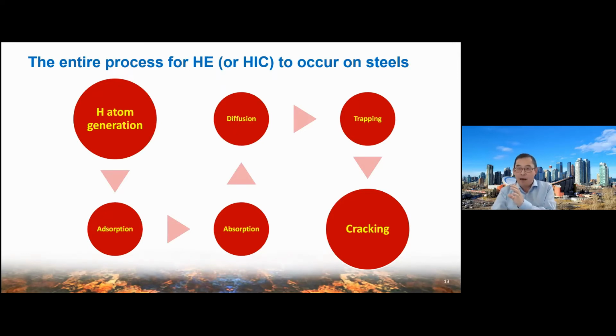All steels usually have typical metallurgical features and mechanical defects, so hydrogen can become trapped. That's step number 5, hydrogen trapping. When the stress, hydrogen and metal structure meet the condition, finally it can cause cracking. So you only have 6 steps at work to cause cracking of the steel because of hydrogen.